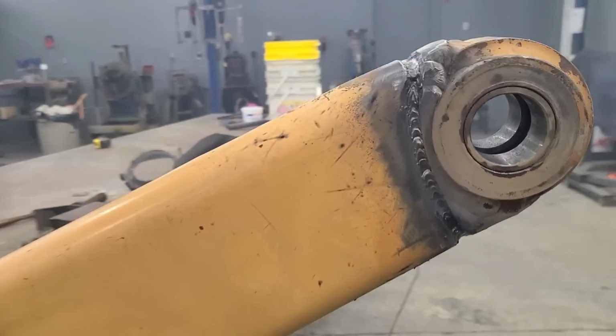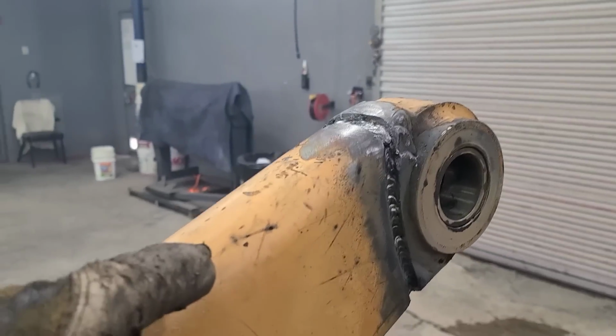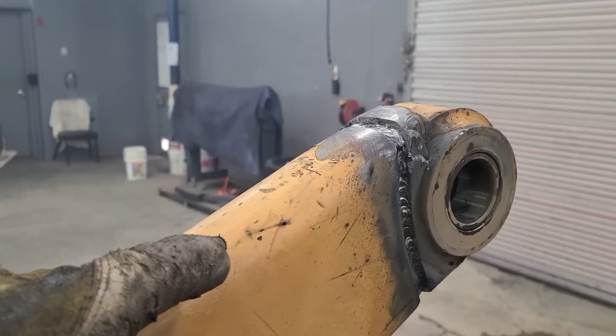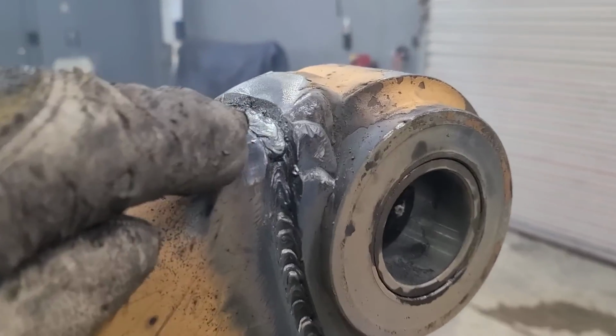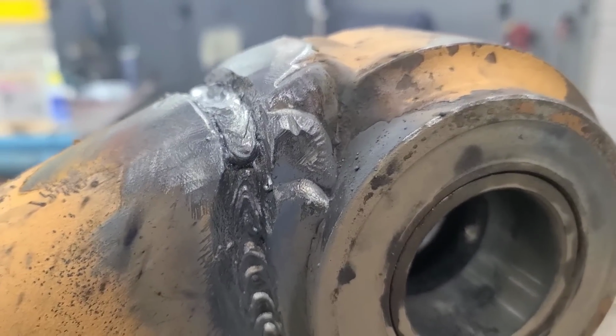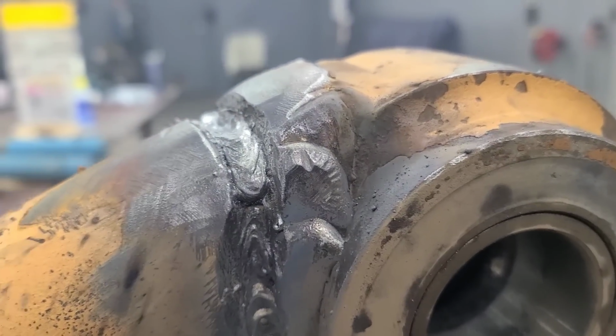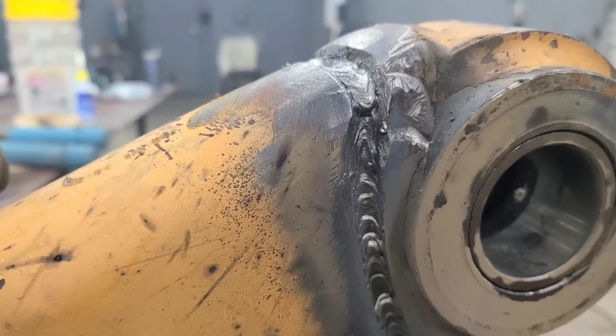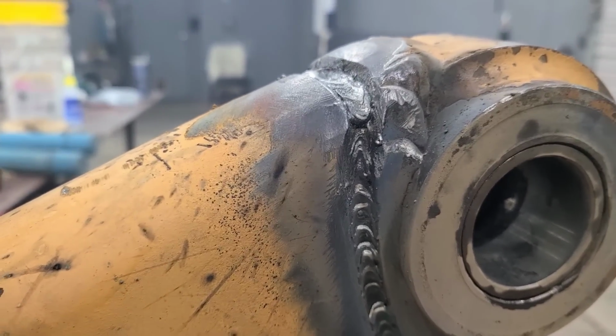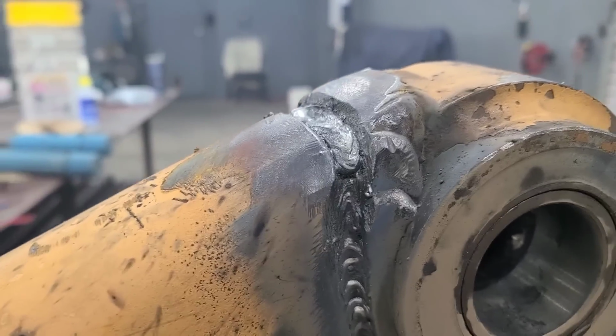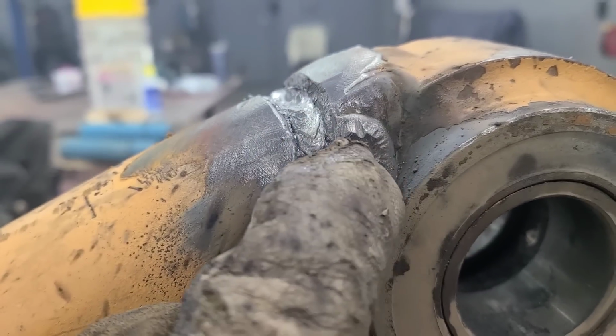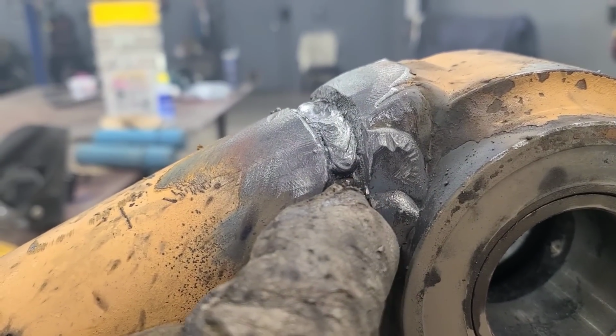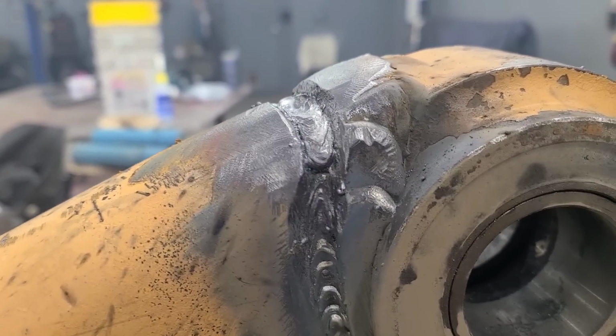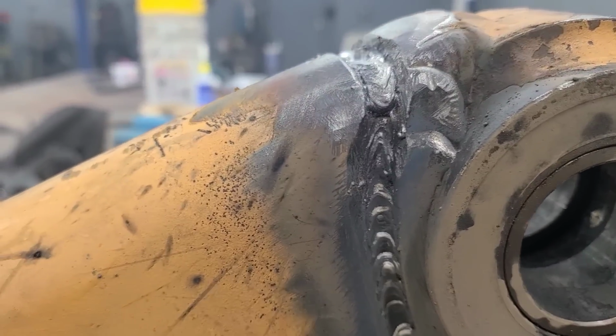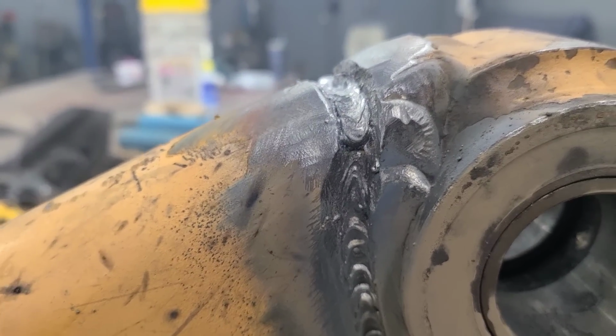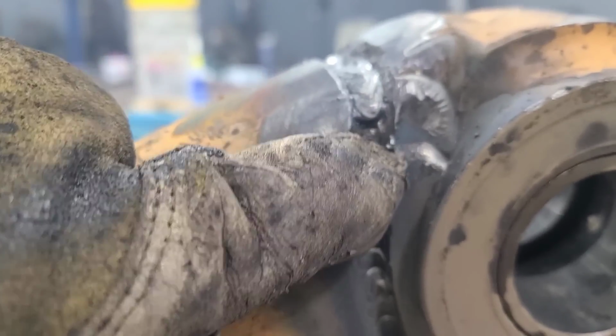Now, I realized before when I was grinding, I didn't really mention why I was grinding. If you look at all the corners, those are where I have starts and stops. And your starts are always going to leave a lump. And that lump should be ground off. See, at the edge of that bump from that start, there's a place that if there's slag there, it's going to be hard for you to burn that out because it's deep. It's clear in under that bump.